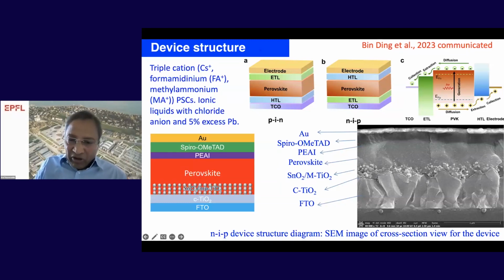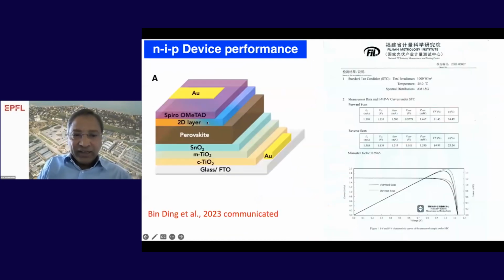Here is the cross-sectional image of our perovskite solar cell, where we have conducting glass, a compact layer of TiO2, followed by a mixed layer of TiO2 and tin oxide. You will see the purpose of having double oxide layers in the charge transport layers. Then there is a 600 nanometer thickness of perovskite layer, followed by a very thin layer of two-dimensional perovskite based on phenylethylammonium iodide. And then we have spiro-OMeTAD as the hole transport material contact. So this particular configuration is shown again.